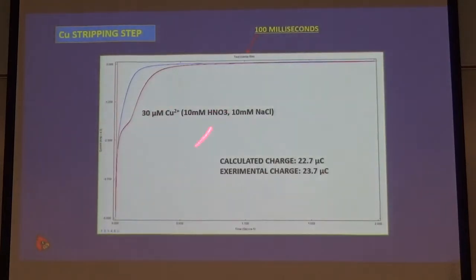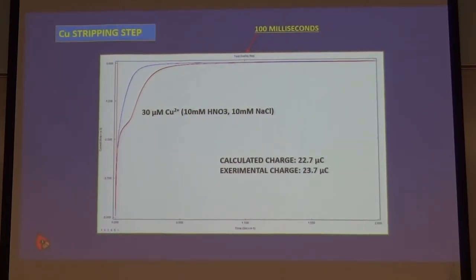So if we go back to this, our signal is going to be the stripping signal. The blue one is the background. The red one is the background plus our signal. So the real signal is simply the area between those two curves. That's the charge that's related to the oxidation and reduction of the copper. And so we refer to this as a crescent. So our signals are always the area of this crescent.